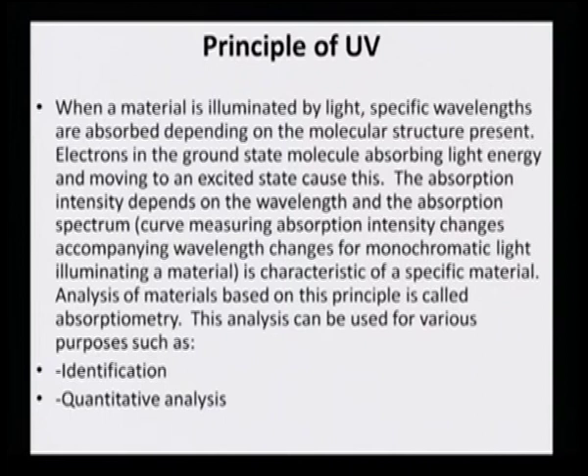This analysis can be used for various purposes: identification as well as quantitative analysis. For now, let us concentrate on identification, because we are learning techniques which can be used for identifying dyestuffs, whether natural dye or synthetic dye. The best way is that monochromatic light is passed through the dye and the lambda max is observed, which is very characteristic of a dye. For example, AR18 and DR80 showed a lambda max of 509 and 543 nanometers respectively.